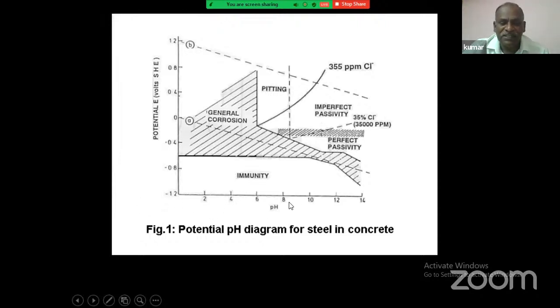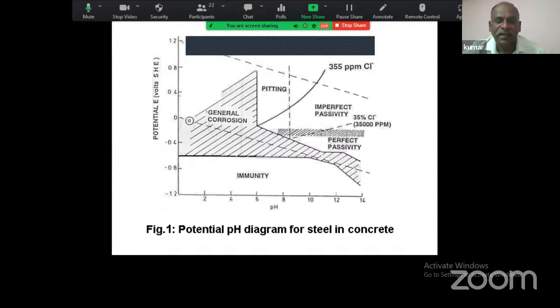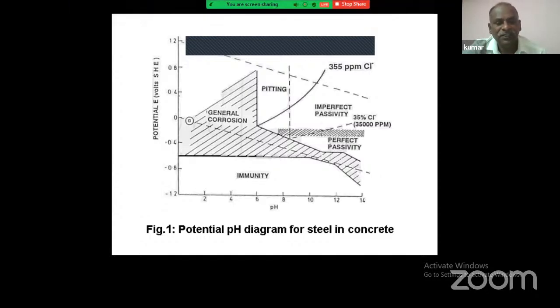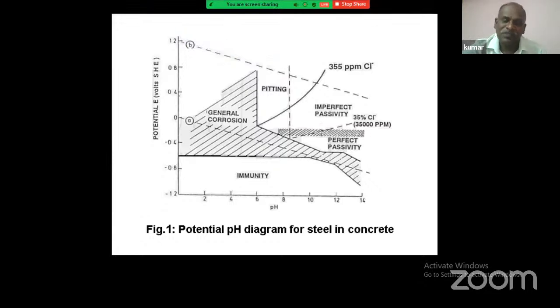When you see the pH less than 7, or less than 6, the potential of mild steel, which we are using as reinforcement, lies between 0 and minus 0.4. This is the region where the potential lies. In these cases, if the pH is less than 6, it will undergo general corrosion. General corrosion means the corroding situation is highly active and the steel will corrode fast, like putting your steel into hydrochloric acid or nitric acid, any acid.